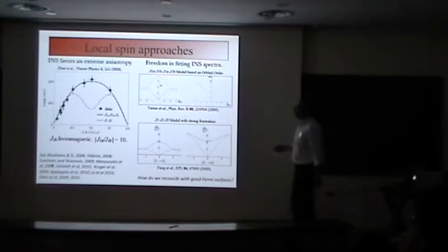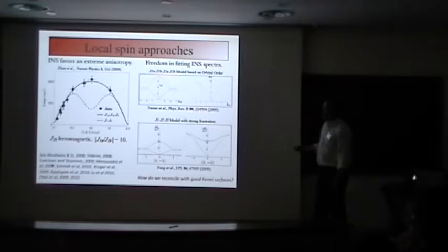So near a critical point, this should produce a local dip around that ordering wave vector. The J1A, J1B, J2 model is unfrustrated, and that has a maximum sitting around pi-0.